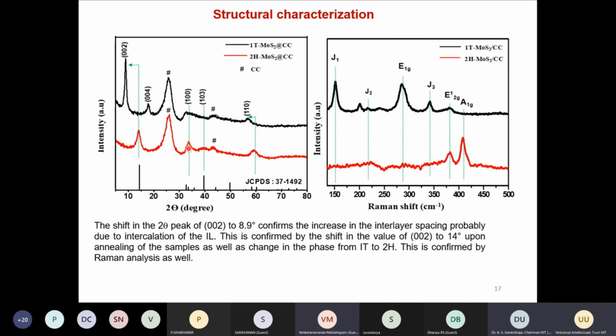This is the XRD pattern of this MoS2 1T phase material, with the ionic liquid intercalated compound. You can clearly see the peak near 14 degrees, which is in the bulk, the 002 plane peak, which shifts to a lower 2 theta value. That tells us there is a very clear increase in the layer distance. This is supported by the Raman measurement, where the E1 2g and A1g peaks are characteristic of the 2H phase. Whereas for the 1T, what we observe are extra peaks which you see only for the 1T phase. So this clearly confirms there is a formation of 1T phase.